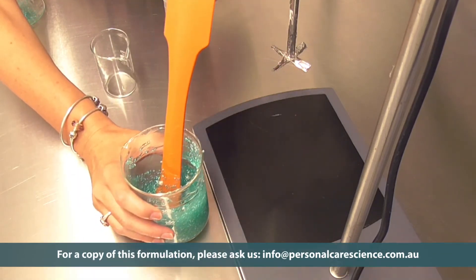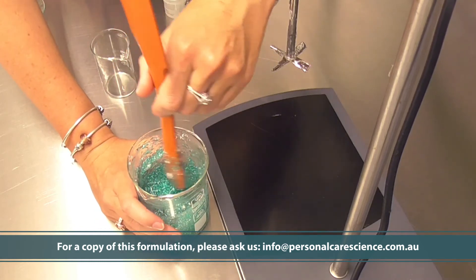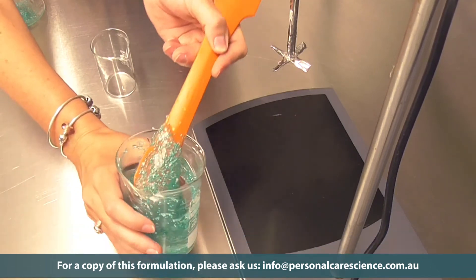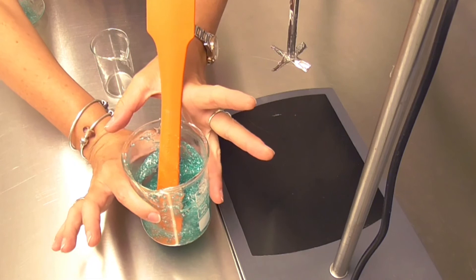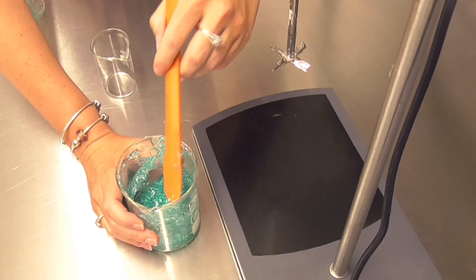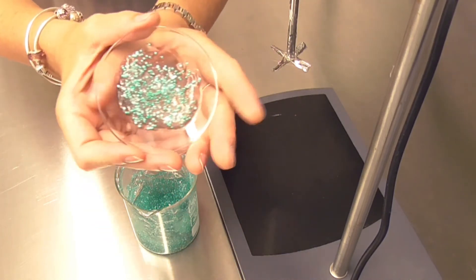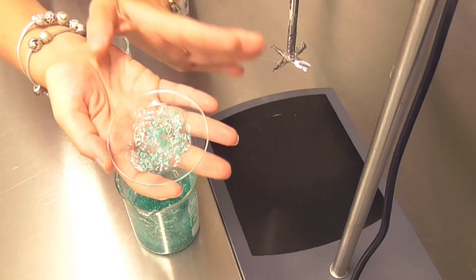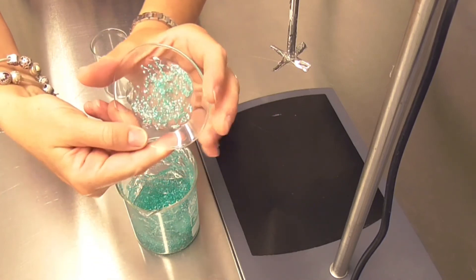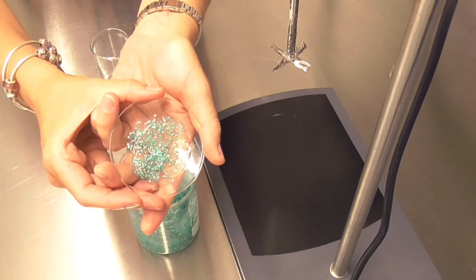Remember: when you make a gel containing a polymer, we can't adjust the final pH, because right now it's a nice viscous gel that's going to stabilize our particles really well. If we adjust this pH we could cause irreversible thinning and lose our viscosity and stability. Also, when you make these types of products you do need to leave them for at least a few days before you send them out to the marketplace, as the capsules need to soften slightly before they'll break easily on application.